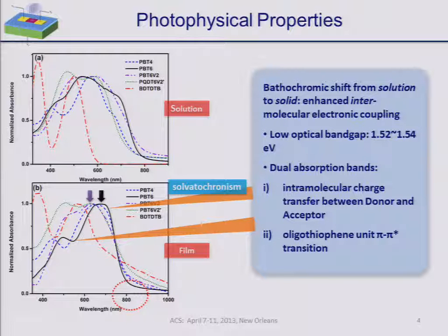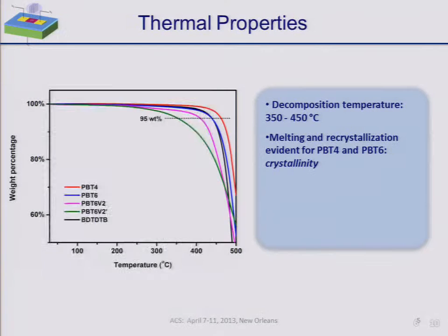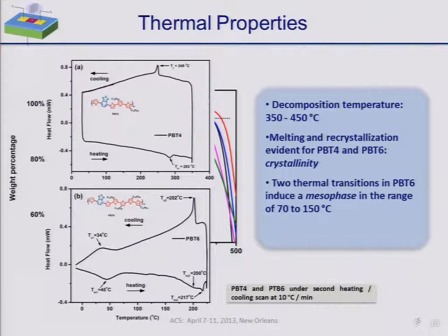You can see that there is some solvatochromism as well as we go from a 4-thiophene to a 6-thiophene analog. Now thermal properties. The polymers are relatively stable. Decomposition temperature ranges from about 350 to 450 degrees C.